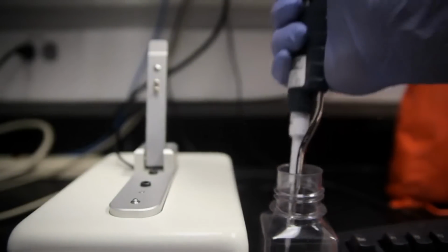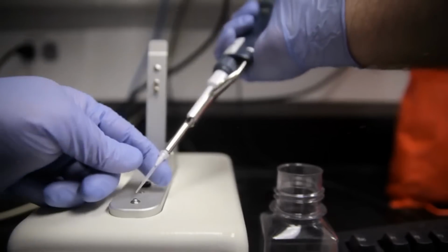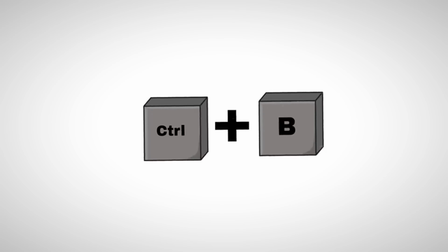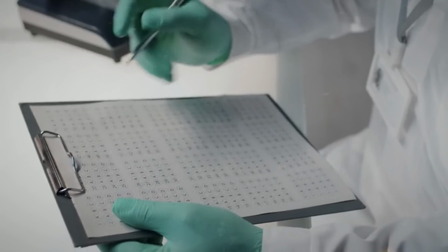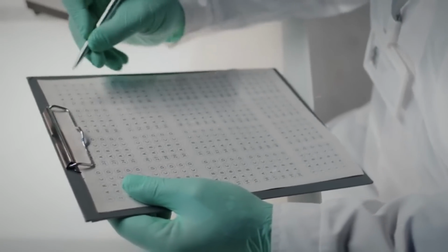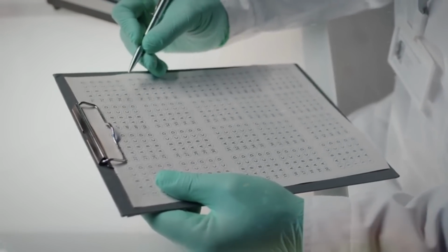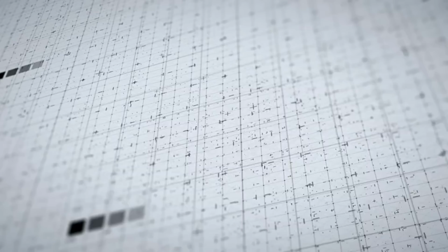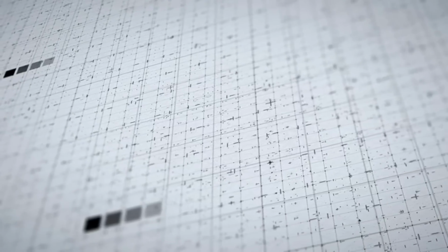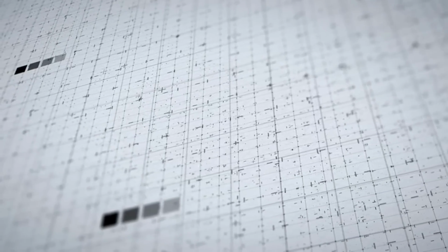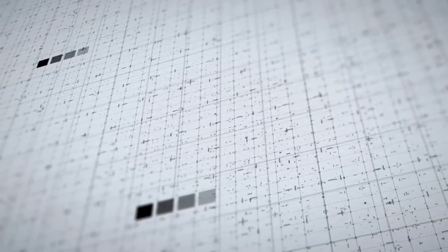Repeatability also includes cross-validation of tools. Each positive sample should be tested with the same field methods as before: thermal probe, UV response, weight comparison, but it's essential to test them blind without bias. Stones should be coded and tested without knowing their grid origin to reduce confirmation bias. Only after these field results are recorded do you recheck them against known samples and lab-confirmed stones.